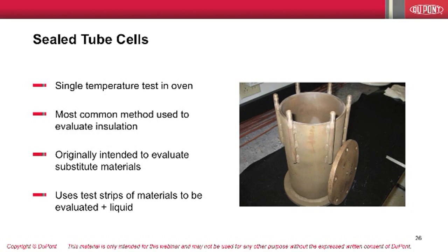This test was originally intended to evaluate substitute materials and has been modified to allow determination of a system capability by changing the determination of the end of life criteria and by extending the extrapolation of the curve to 180,000 hours from the original 65,000 hours.